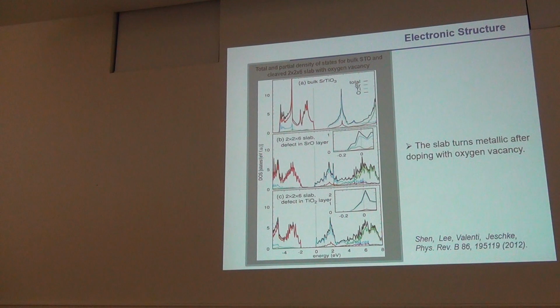And basically what we find is that these 2 electrons that come from your vacancy are in fact giving you conduction. And I'm showing here a blow up at the Fermi level where you see that now you start feeling the d orbitals of titanium. So this is of course a fraction of d, but the electrons start to feel these d orbitals, and moreover, since you are seeing this metallic state, what it's telling me is that these electrons are forming extended Bloch waves. So they are producing conduction. So in principle, this is going in the direction of what the experimentalists are observing, that we seem to have conduction coming from these oxygen vacancies.